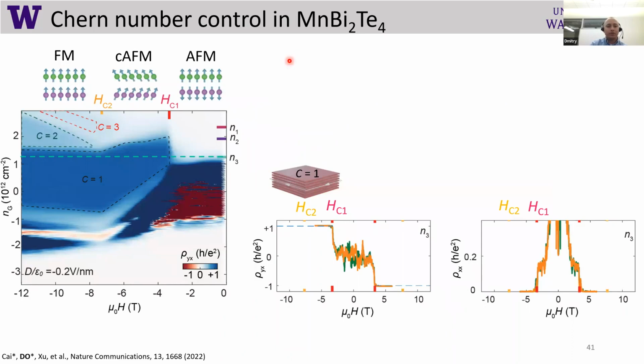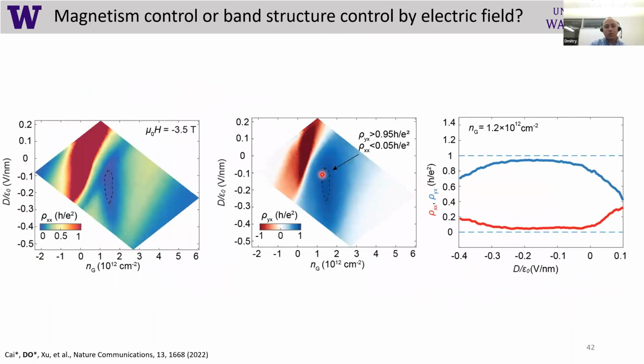One more thing I want to pay your attention to is this sweet spot here, which indicates the transition from trivial to non-trivial topological insulator. So Chern number 1. What we can do when we sit at this transition, we can fix the magnetic field, and then we can sweep our gate voltage. We have a dual gate geometry, so we can change electric field and carrier density inside the material. So what we find is that there is a place in this diagram, essentially here, in which Chern number is approaching 1, but we can also get away from 1 by changing electric field and also carrier density.